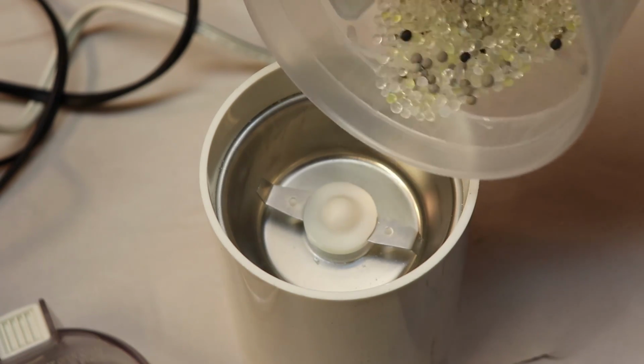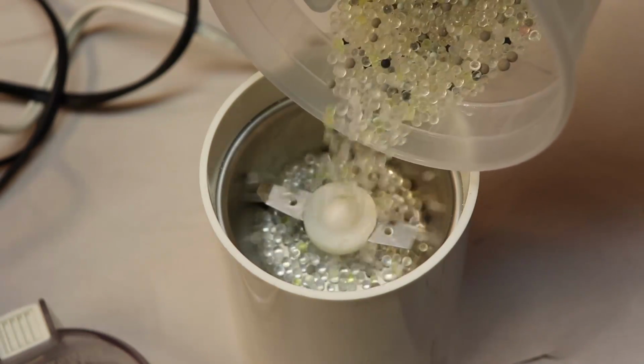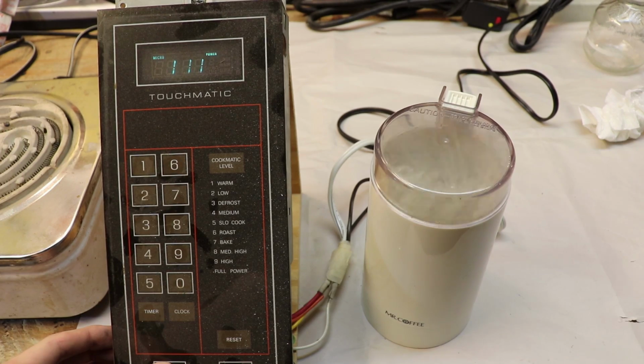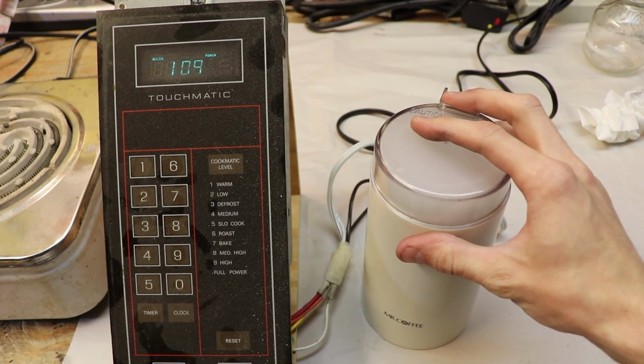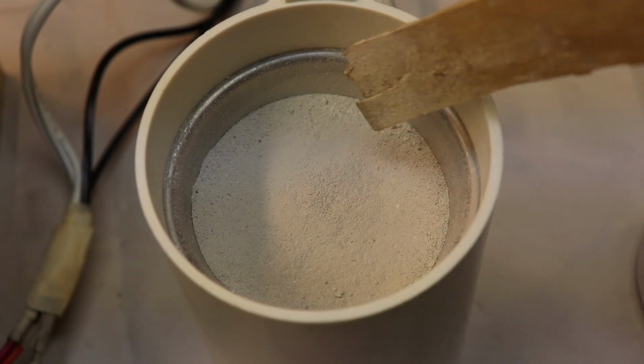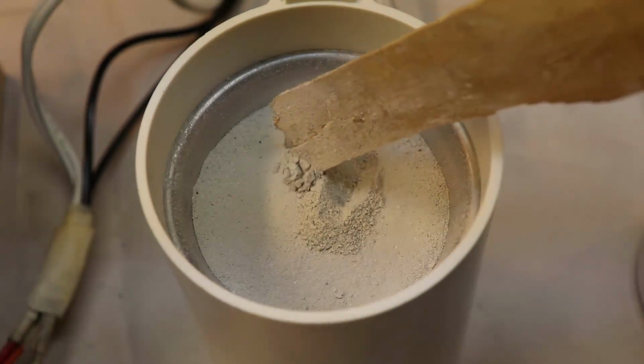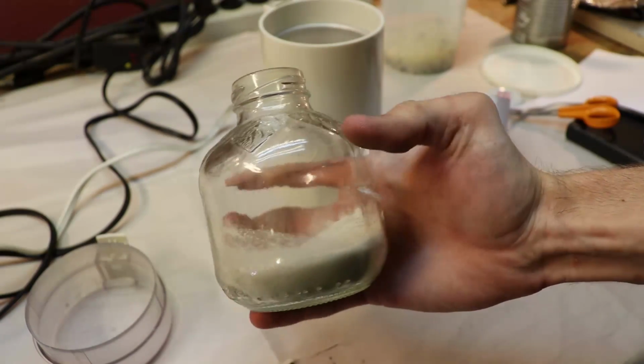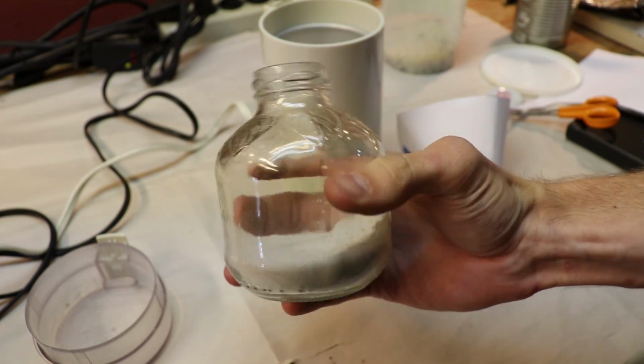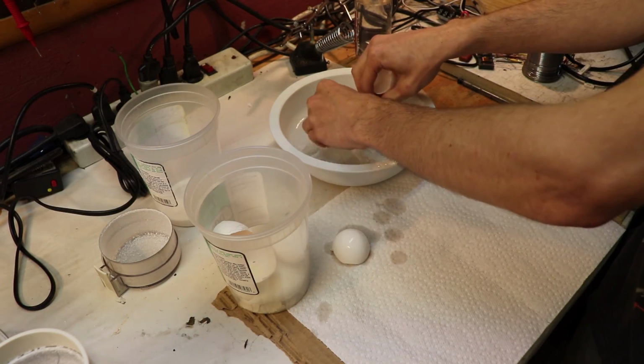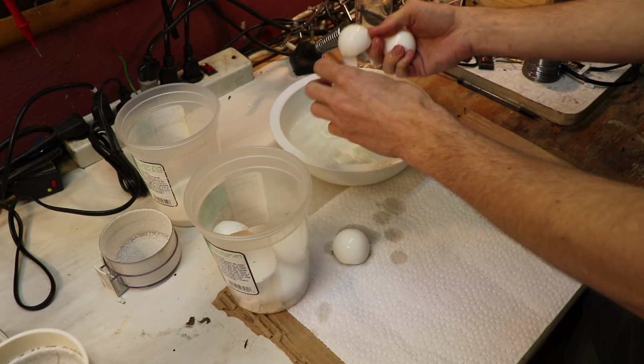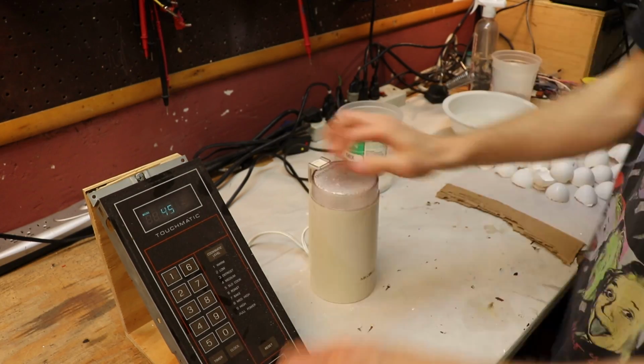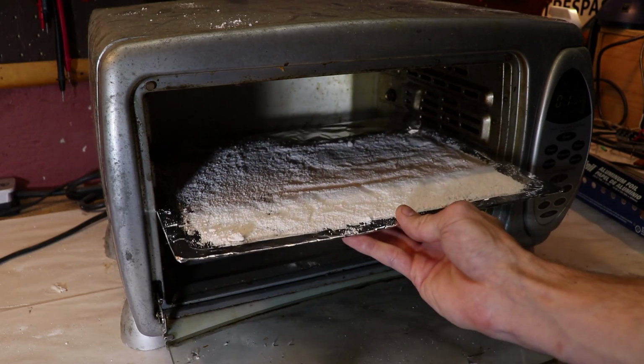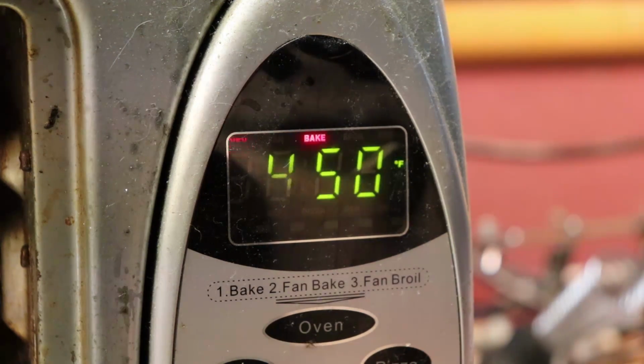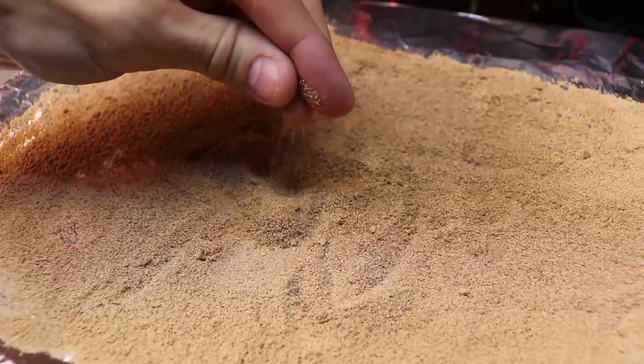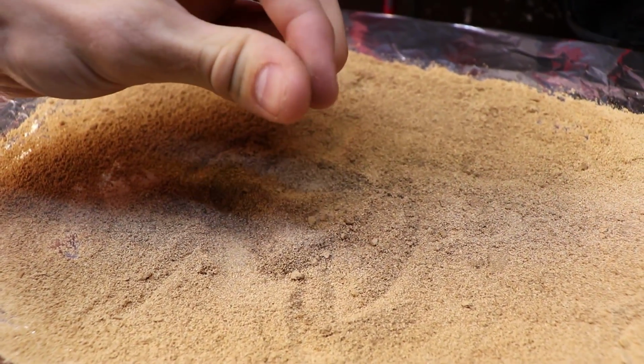So to make the sodium silicate, I took the silica gel and shredded it in a coffee grinder. This will make it easier to mix later, but you seriously do not want to breathe this stuff in. I wore a mask and very carefully handled the powder, letting it settle after shredding before I put it all in one glass container. I also cleaned the eggshells by rinsing them first in warm water and drying them out. Then I also shredded them and later baked them at 450 degrees Fahrenheit for 30 minutes. That turned them into a nice golden brown color and got rid of any smells.